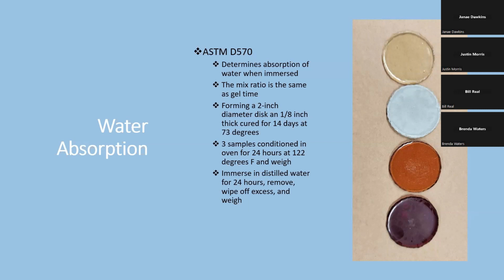So if you look at the picture, there are different types and different colors of products that you may have, but the discs are all going to be made in the same way. The only thing you're doing differently is that instead of pouring in a Dixie cup, in this instance you use a small aluminum pan. And every time you do the test, you always work in threes. You're going to do 3 samples, condition them in the oven for 24 hours at 122 degrees, and then weigh them. You're going to immerse them in distilled water and leave them there for 24 hours. When you remove them, you're going to wipe off the excess, weigh them, and then record your result.